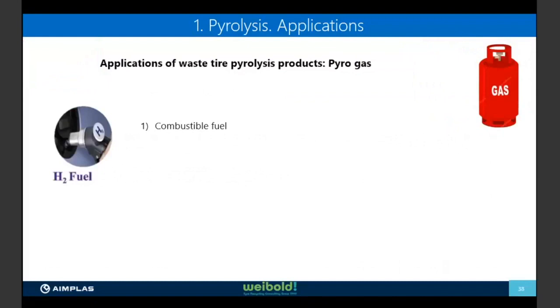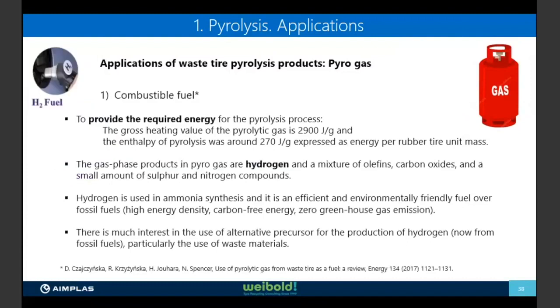Okay, and the application for the third fraction of pyrolysis, that is the pyrogas, is mainly as combustible fuel, okay? Because I have already said that the main gas in this fraction is hydrogen. Okay, so from this fraction we can provide the required energy for the pyrolysis process. The gross heating value of the pyrolysis gas is 2,900 joules per gram, and the enthalpy of pyrolysis was around 270 joules per gram, expressed as energy per rubber tire unit mass. So the gas-phase products in pyrogas are, as I said, mainly hydrogen, and also a mixture of olefins, carbon oxides, and a small amount of sulfur and nitrogen compounds.